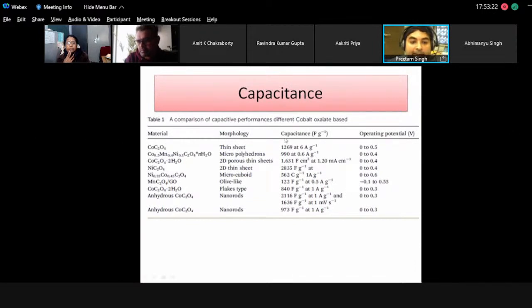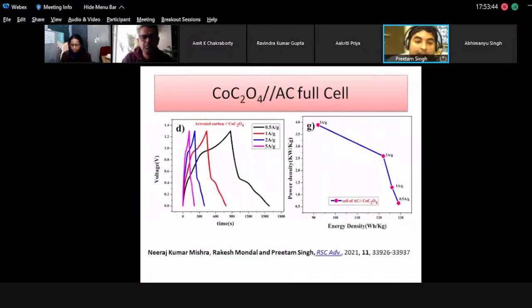And the capacitance we are reaching is almost 1269. This one is already known, and our material, the anhydrous nanorods, is showing around 2116 Farad per gram. And even if we use Na2SO4 electrolyte, it is going to be 973 Farad per gram. So in the aqueous electrolyte the performance is very high, and when we make the full cell, we are able to reach an energy density of around 130 watt hour per kg to 90 watt hour per kg, ranging from half ampere per gram to 3 ampere per gram.